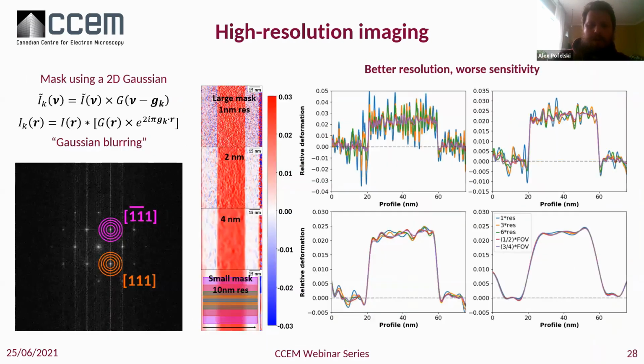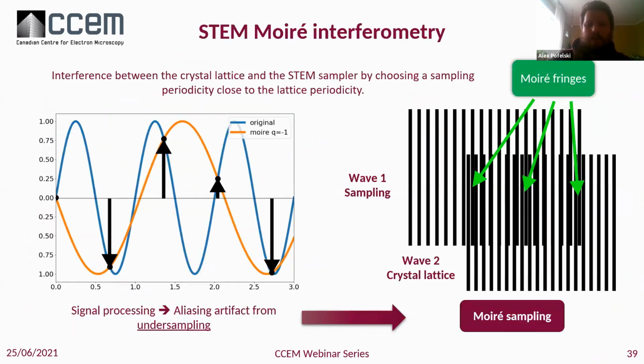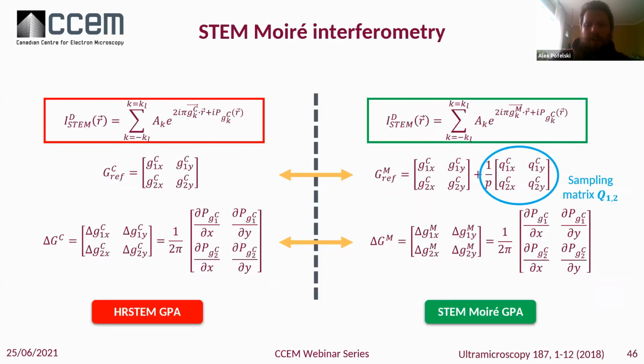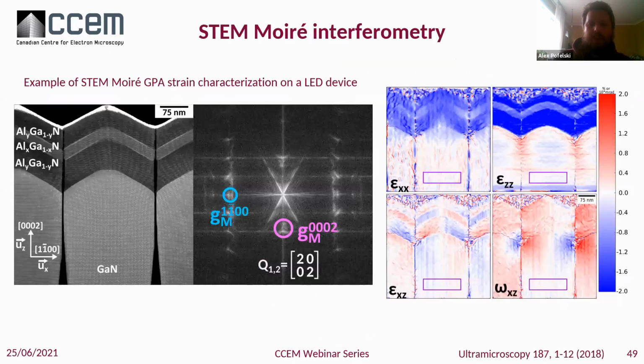The one thing I will comment on, because this is a good comment, regarding this large field of view: this is, for example, the Fourier transform of that structure we have on the left. You can see that we are supposed to have dots, but we are so sensitive to the deformation that we have some extension of them, which makes the Fourier transform look like it has some structure. And this is related to the strain distribution in the device. But definitely, Fourier transform based methods include all the deformation inside.